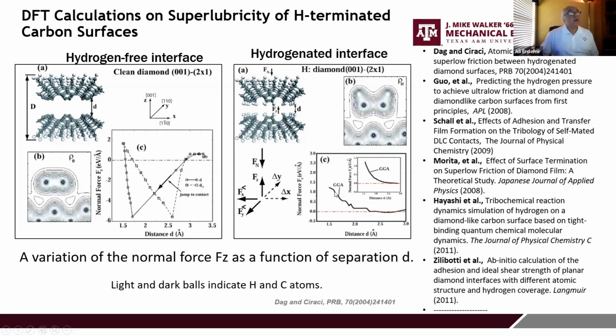So this was one of the very first simulations, but other colleagues from different places also did similar simulations to show that indeed these highly hydrogenated, or hydrogen terminated, carbon surfaces will trigger huge repulsive forces as you bring them closer to the contact situation.